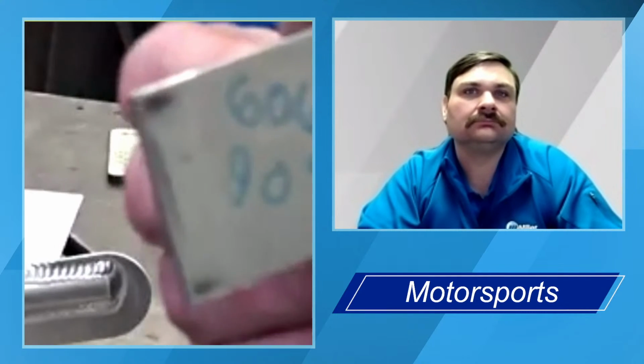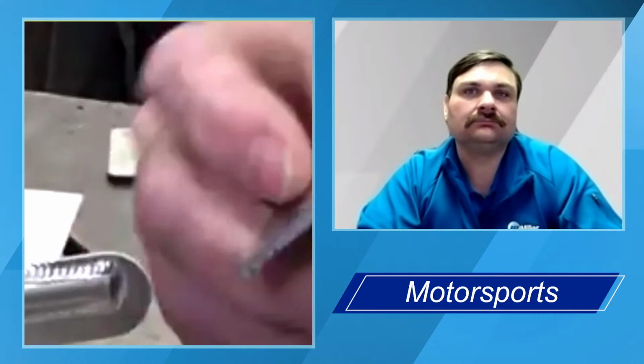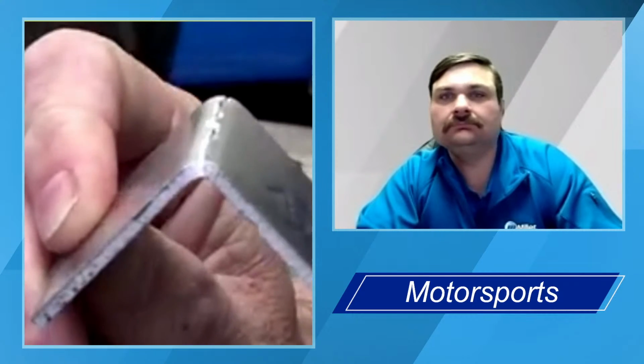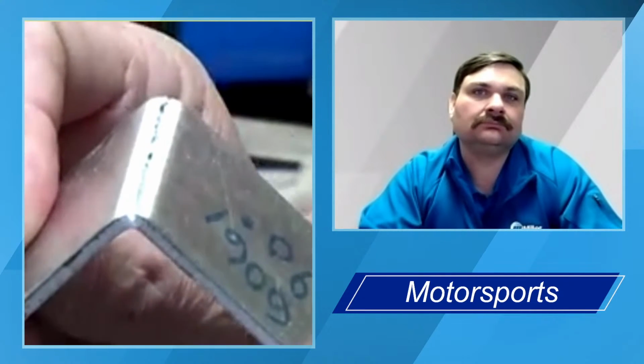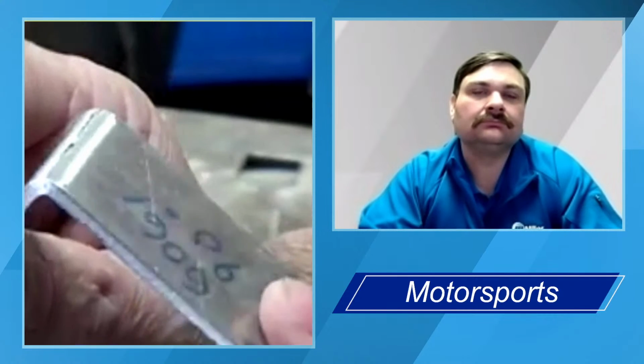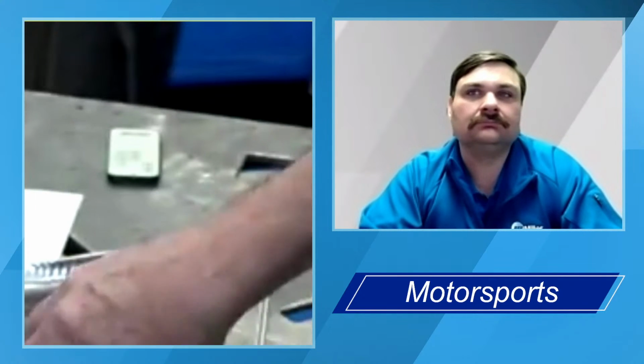But I guess one of the other things that I want to say about aluminum is that a lot of people, even in the performance industry, think that they should use some of the strongest aluminum for their projects. And sometimes that's not the case. Unlike steel, where even your higher strength steels can be formed in a brake press, or you can fabricate it, bend it, roll it, with aluminum, that's not necessarily the case. A good example of that is just using different alloys. Like 6061, for example, is a very strong alloy of aluminum, but as soon as you try to bend it, and this one's being bent at a 90 degree, you can see that it's already formed a crack. So even though 6061 is an extremely strong aluminum alloy, it's not good for bending and forming applications.